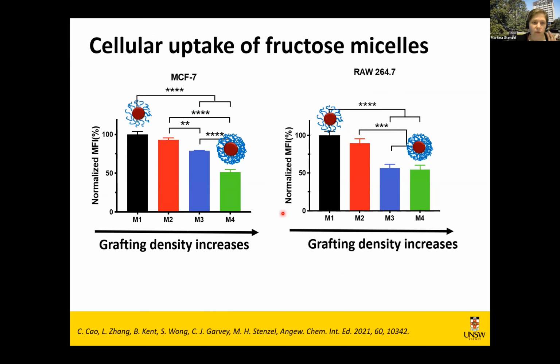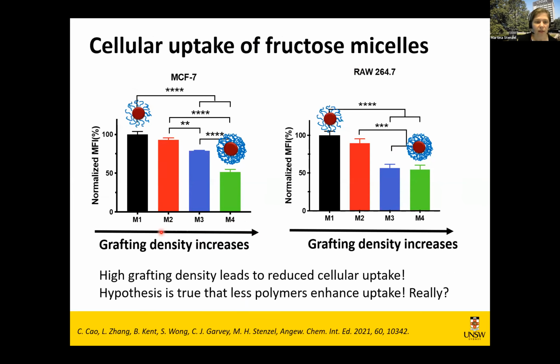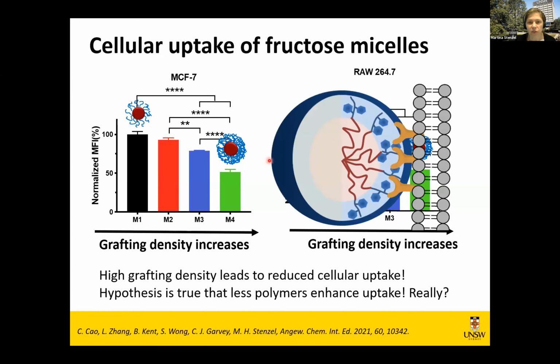So now again, we take these nanoparticles, we incubate them with cells. And what we find is that we have indeed a much higher cellular uptake with the low grafting density. And we do that in various cell lines. It's always the same. So it almost feels that the high grafting density led to reduced cellular uptake. And at this point in time, we can probably be pleased with ourselves because we said, well, our hypothesis is true. So if we have a bit more space, the binding with lectin is better.